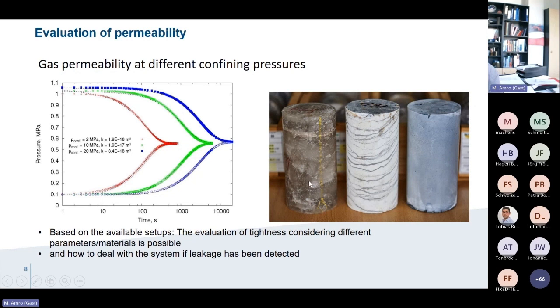Here we have a salt sample, for example, caprock, anhydrite, and cement, and we can identify the permeability. This is only one example, gas permeability at different effective pressure or different confining pressure. You can see the higher the confining pressure, the lower the permeability.